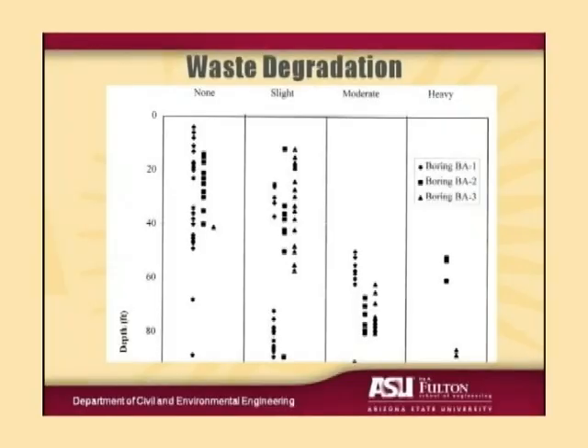You see this general trend of increasing degradation with depth, but you also see that it's a little bit scattered, that sometimes at very deep depths, at the dry end of the landfill, we would have waste that showed no sign of degradation. Other times at shallow depths at the wet end of the landfill, we would see a high level of degradation. And that's very consistent with our knowledge of waste degradation, particularly in arid and semi-arid areas where the degradation is limited by the availability of moisture. So where we had moisture, we had heavy degradation.